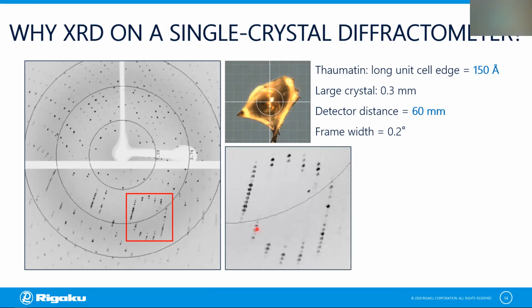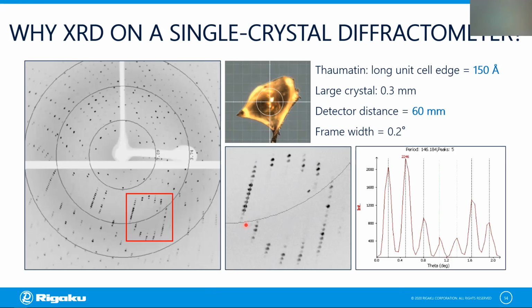So if you look at that area of the diffraction image, you see that the reflections look well enough resolved. Again, I drew a line along that row of reflections to get a two-dimensional plot of the intensity distribution along that line, and this is what I see. In between reflections, the intensity comes back down to zero or almost, showing that the reflections are well enough resolved. And sure enough, we got a beautiful structure out of that crystal.